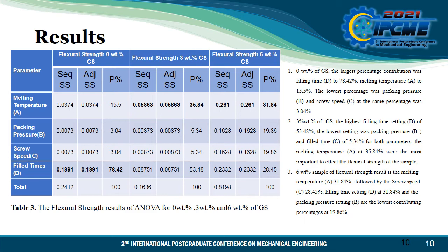the melt temperature. For the 3% Gigantochloa Scortechinii, the highest was filling time, which has a value of 53.48%. The lowest is packing pressure, and packing pressure is 5.34%. And the melt temperature for the 3% natural fiber is 35.84%.